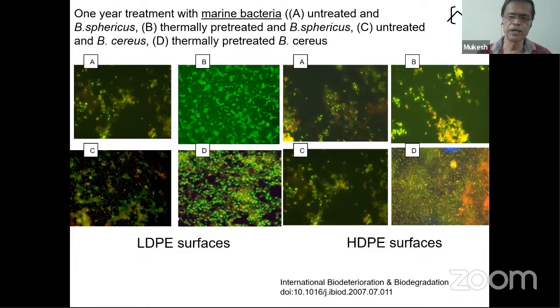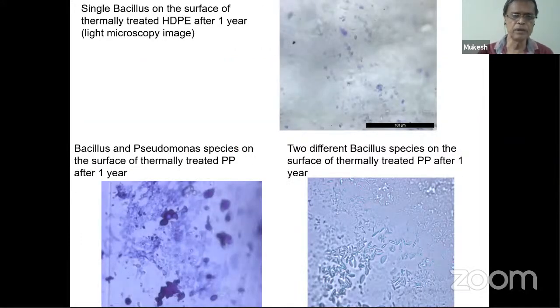And that's a very important precondition before we achieve degradation, because bacteria has to proliferate and give out enzymes which can help in the degradation of the material. So a low density polyethylene can degrade better over a period of time compared to high density polyethylene, because as you can see, the bacteria is able to sit nicely and proliferate over a period of, this is about a 1 year study actually. Again, more number of organisms found in the marine environment, like Pseudomonas, Bacillus, all over a period of 1 year after they are thermally treated.